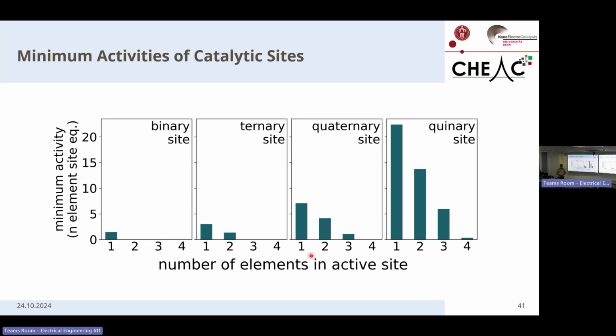For a 5-element site to outperform its counterparts, it needs to fulfill multiple rules. It needs to outperform its pure metal counterparts by 22 times, its binary counterparts by 14 times, and its ternary counterparts by 8 times. So these numbers without any context don't mean much.